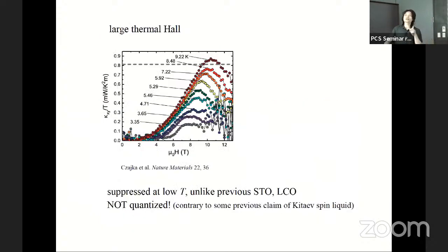Okay, so the large thermal Hall is again very large, of order 1 in the natural unit. But it's different from the previous STO and LCO. In the STO and LCO, at low temperature, it has some power scaling with the temperature. Here, it's suppressed at low temperature and only starts to ramp up at around 5 to 10 Kelvin.